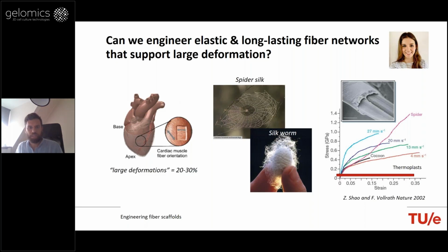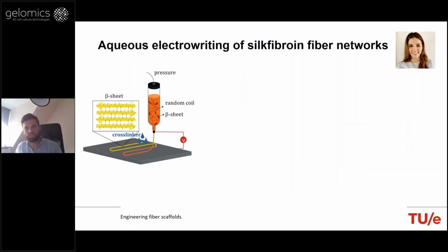We advanced the principle of electrowriting towards an aqueous electrowriting process. So here we created basically a hydrogel type of silk fibroin ink, and then we investigated how it can be processed under room temperature using in the presence of electrical fields in order to achieve the same small fiber diameter polymer filaments, and keeping the same ability to pattern, so achieve an accurate design of your printed constructs, because that is quite relevant, as